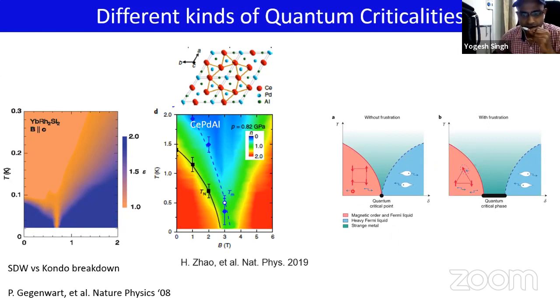So if you had an unfrustrated lattice, then on this side, where the Kondo screening is not strong, you will get long range order. But as the long range order is suppressed, you enter a heavy Fermi liquid, where the Kondo singlets govern the physics. On this side, if you had a frustrated lattice, what would happen as you are coming in from the heavy Fermi liquid is that because of the frustration, the magnetic order cannot condense, and therefore this phase is pushed down in phase space. So the ordered phase happens only when the frustration is lifted by a quenching of the formation of one of the singlets, for example. So there are very interesting open questions even in the quantum phase transitions in heavy fermion materials. That is the reason we wanted to study this.